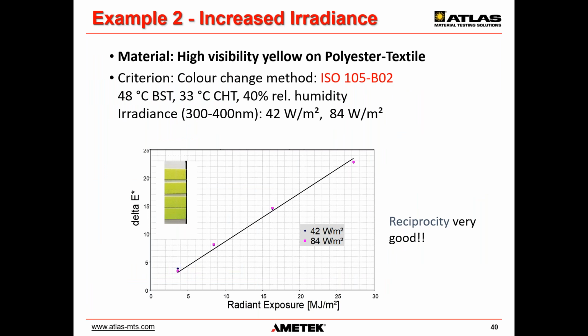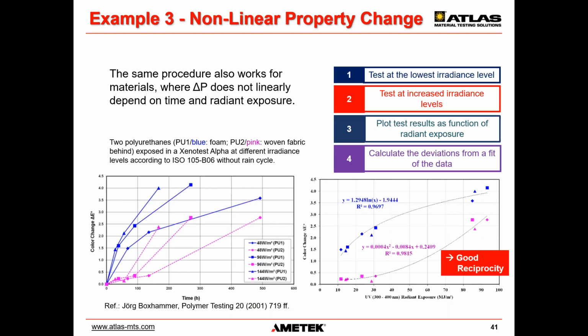Another example, a bright yellow textile for safety garments. This time, two irradiance levels were used, 1x 42 and 2x 84 watt per square meter. Again, when the color change was plotted against radiant exposure, the reciprocity was very good, as shown by the linearity of the graph. The same procedure also works for materials where the property change does not linearly depend on time